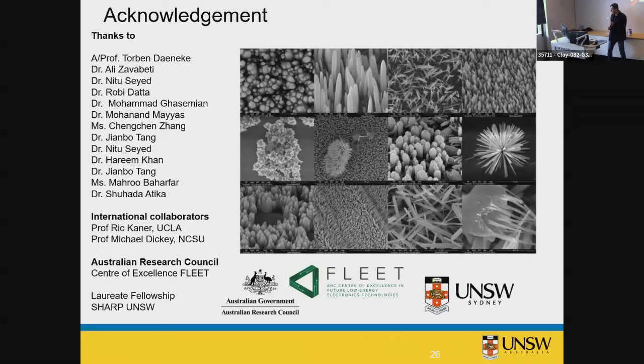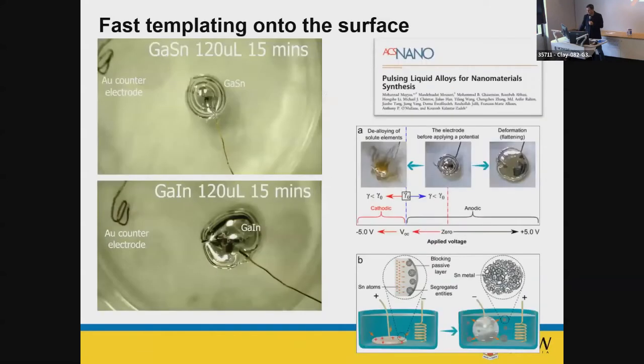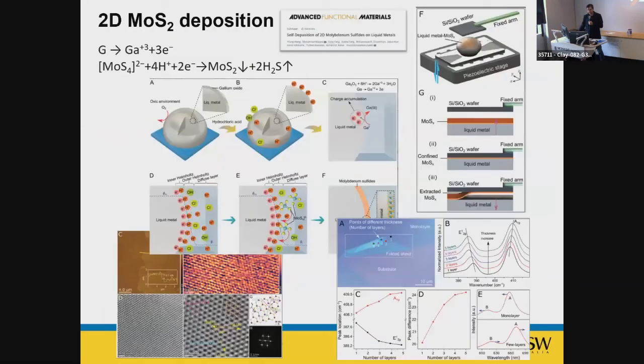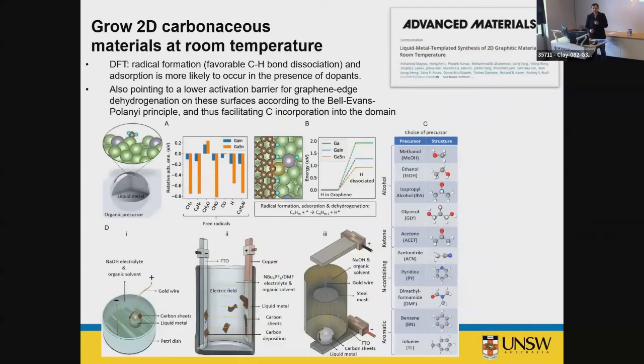Yeah, that's a very important question. First of all, we have oxide. Oxide is not always our friend, sometimes our enemy, because it basically buffers the very active catalytic surface of liquid metal. We don't want that. So, for instance, if you remember, I mentioned that we used acid, right? And here, we use acid to produce gallium 3+. So they go, and then we have a precursor of molybdenum disulfide that produces the molybdenum disulfide on the surface. Or here, it was done in a basic environment. We have NaOH to get rid of that oxide again.